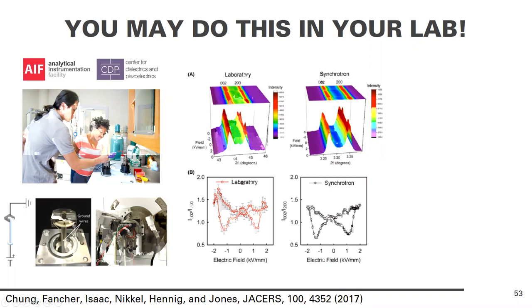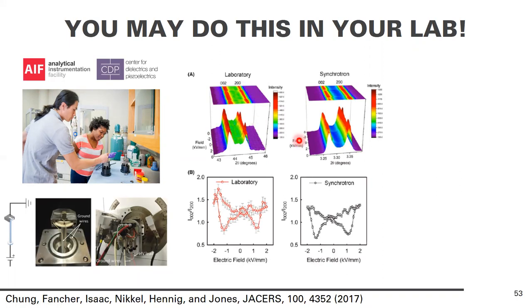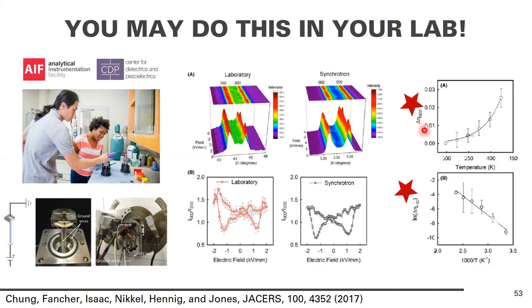Representative data is shown here. Laboratory data for a given sample matches well the synchrotron data. It's a bit more noisy, but you don't have to travel to a synchrotron and you can do it during a pandemic. And then what we plot over here is delta eta as a function of temperature. So you can see the extent of switching in this particular sample increases with temperature as you'd expect. And then we fit it to determine an activation energy.